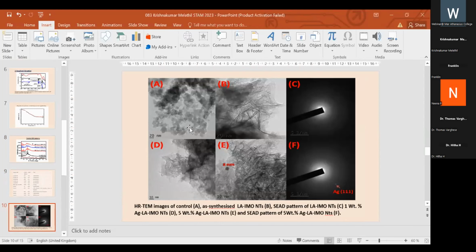Here we can see that in the case of blank IMO-NTs, there are some circular shaped formations of aluminate and silicon nanoparticles. But in the case of lauric acid functionalized imogolite, we can see the formation of some tubes on a lauric acid bed. Actually, lauric acid formed a layer, and on that layer we can observe some tubes.